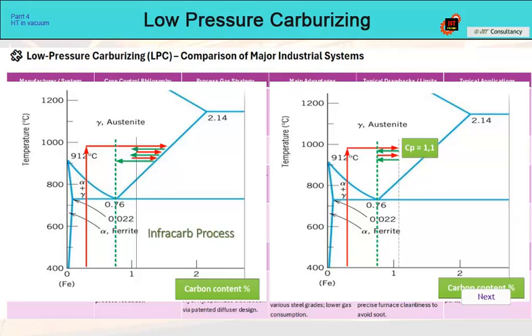In this, the ECM system is exceptional because it uses auto-regulation of the kinetic equilibrium of the carbon flux in the furnace by reaching the ACM line, with the exclusion of iron carbides Fe3C. This is also the reason why we do not need to know the area of the charge with this system. And not only that, the LPC control guarantees that we will constantly move in a stable area of carburizing without ethylene formation and without soot deposition.